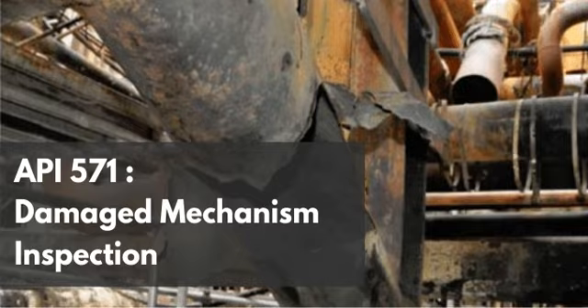Okay, so break that down for us. What is the mechanical reality of creating a weld? Well, think about it. You're introducing a localized heat source approaching 3,000 degrees Fahrenheit to melt the steel. That's a lot of heat. Right. And that liquid metal pool expands, but it's surrounded by a massive heat sink, the cold, unyielding base metal of the pipe or the vessel. So what happens when it cools? As that weld pool rapidly cools and solidifies, it desperately attempts to contract. However, the surrounding cold steel acts like an immovable vice. It prevents that natural thermal contraction. Ah, so instead of shrinking, the weld metal and the immediate surrounding base metal are subjected to this immense permanent tension. Exactly. They are locked in tension.